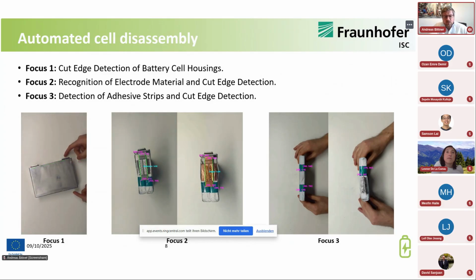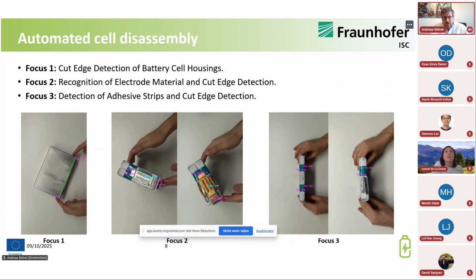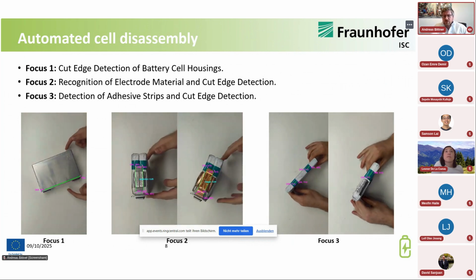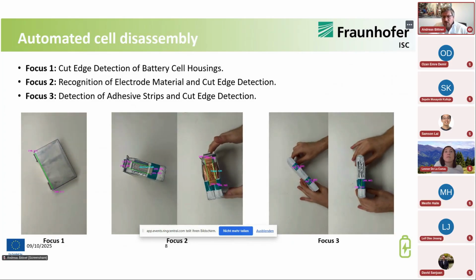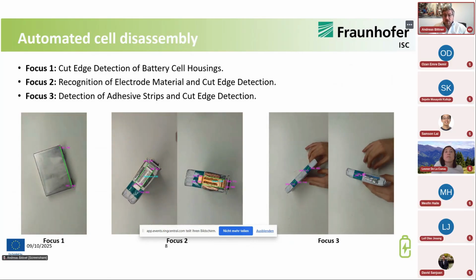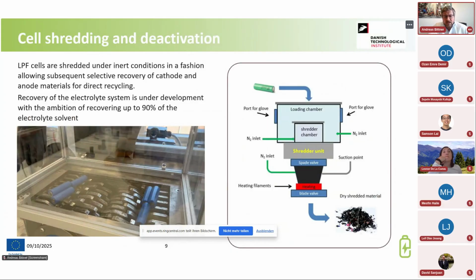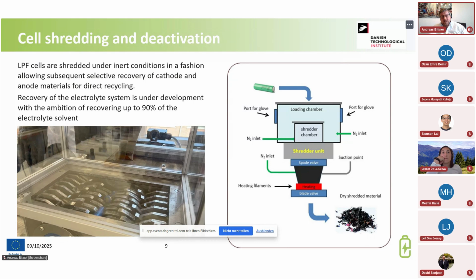An example for the alternative route is shown with a lab scale shredder that was developed by our partner DTI. And on this scale, we are able to adjust the configuration of the shredding very quickly, very cost efficiently to really separately recover anode and cathode materials out of the shredder. On the right hand, you can see the design of the system. So it includes a closed system with an inert gas atmosphere to ensure that we have no explosions, to ensure that we can also recover the electrolyte, and to ensure that materials are not harmed in this system.